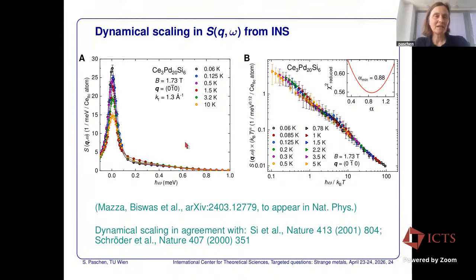So you see the data here. That's the raw data, cleanly separated from any background and put into absolute values here with normalization procedures. And then we take these data and try dynamical scaling analysis that were already introduced much earlier by Almut Schröder, and there's also theoretical work on this by Qimiao Si. And we see that dynamical scaling relationship with now an exponent that is smaller than 1 is again found here over many orders of magnitude. So it's quite a robust scaling that is found here that would be consistent with this picture of Kondo destruction, where you have the clear idea of what this Fermi surface reconstruction means.